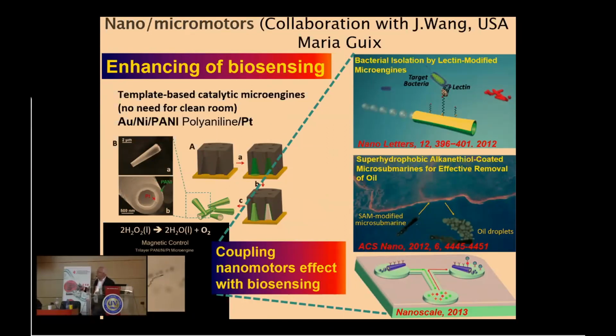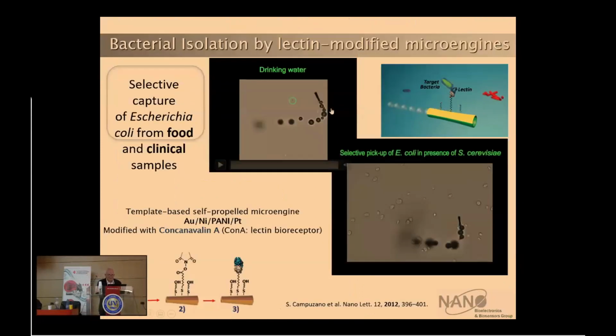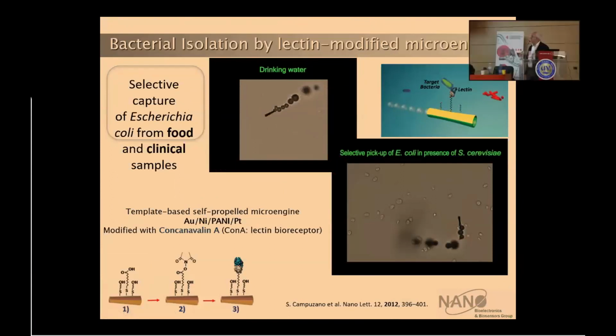What you see here is that these motors contain some catalytic materials, like, for example, platinum, and they are able to transform hydrogen peroxide into water and oxygen. And this oxygen is serving as a propulsive force. And you see here these tiny motors move because the bubbles are coming out, and by having some magnetic properties, we're able to move the orientation of these. You see here better.